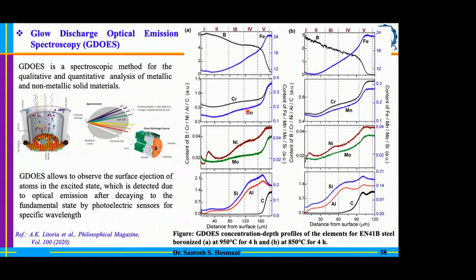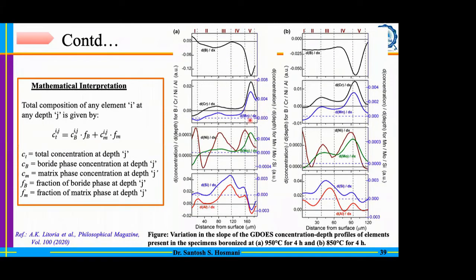And that is what we need to understand. For that purpose, we took the slope of this particular profile, and we wanted to understand how the slope varies. And here is the slope variation. You can see that for the boron profile, look from V to I, that means from core to surface. There is a decrease in the slope, and then it again migrates toward zero slope. That tendency is aggravated at elevated temperature, that is, 950 degrees Celsius.